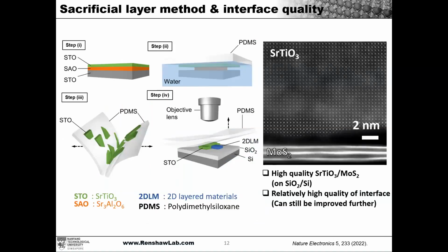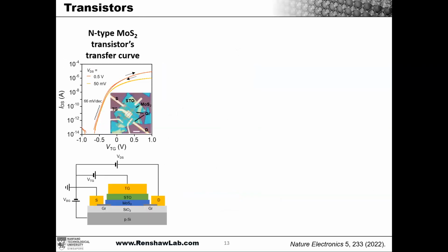Studies and progress. So then we solve it with a technique. We use the transfer technique: we stack the oxide and the 2D materials together. Simple, straightforward, right? The interfacial quality currently within our group is still not super high yet, as you can see. There's a little bit of a gap between the 2D materials and the oxide. But if you look at the quality of the oxide membranes, it's quite good. So the functionality is there. Although there's some interfacial problem to be further improved, let's just move forward and see what we can get.